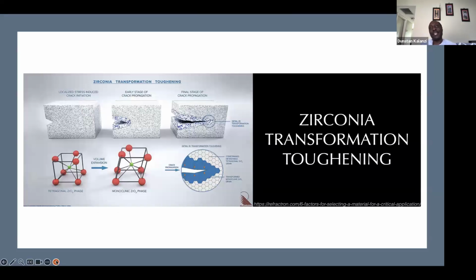So zirconia, one of the advantages that it has is the property called transformational toughening. If your material develops a crack, this material can arrest the crack. And how does it do it? Around the tip of the crack, the material transforms from the unstable tetragonal phase to the monoclinic. And when it transforms into the monoclinic phase, it causes a volume expansion of about 3 to 4%. That expansion generates compressive stress. It is that stress that arrests the crack. So it stops the propagation of the crack.